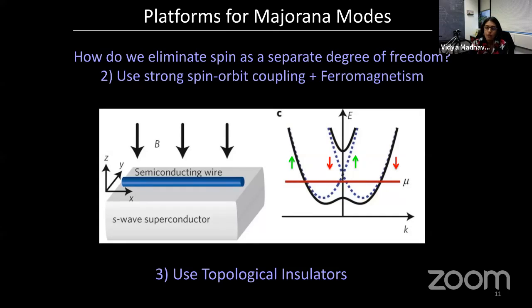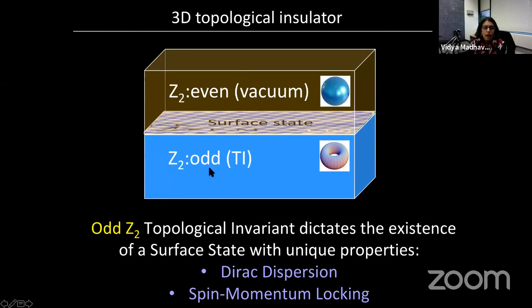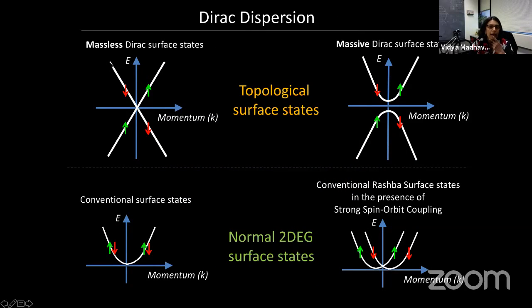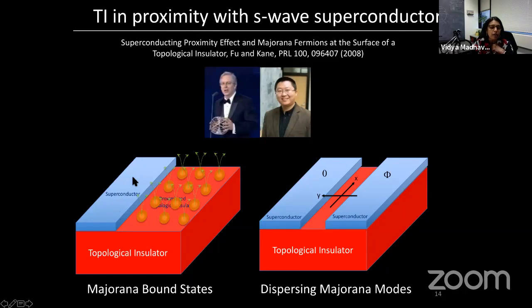The other possibility is that you can use topological insulators. I mentioned this before, but a topological insulator is a material where the non-trivial topology of the bulk dictates the existence of very special boundary states. So for the case of a 3D topological insulator, you expect to have these very special two-dimensional surface states living on the surfaces of the system. The interesting thing about these surface states is that the dispersion is linear, close to the Dirac point, and also that the electrons have the same property that I mentioned before, which is spin momentum locking. So if you could take a topological insulator and proximatize it with a superconductor, then you can achieve a situation where the excitations are Majorana fermions.